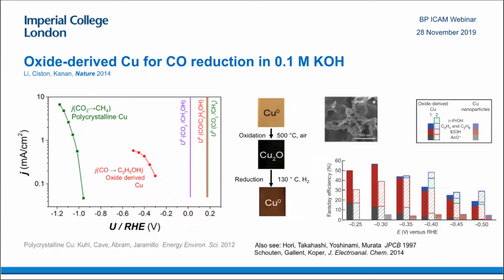So the next question is, how can we reduce CO further? There's been some very interesting work from Matt Kanan. What he found is if you took a polycrystalline foil and oxidized it, then reduced it, he made what he called oxide-derived copper, which had a very high surface area, kind of a skeletal structure or foam of copper. What we found is if you put that into a very alkaline electrolyte, you'd make ethanol. Ethanol is a much more desirable product than methane, which the polycrystalline copper normally makes.